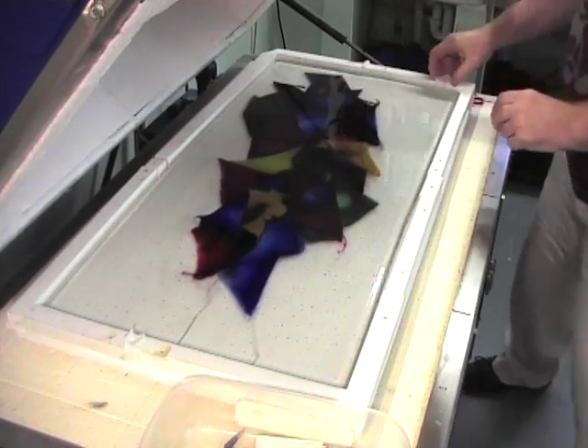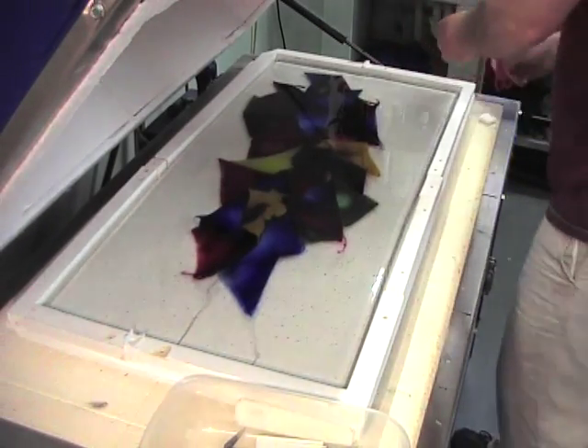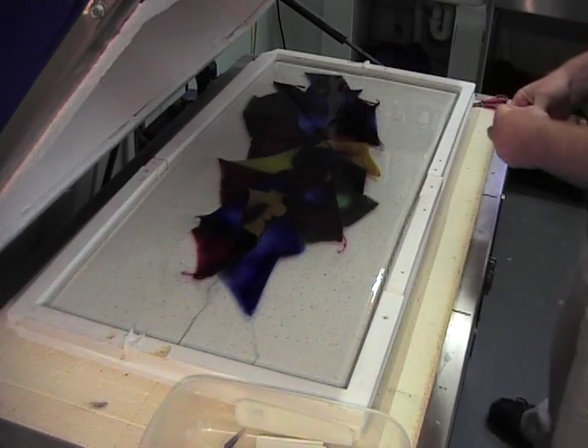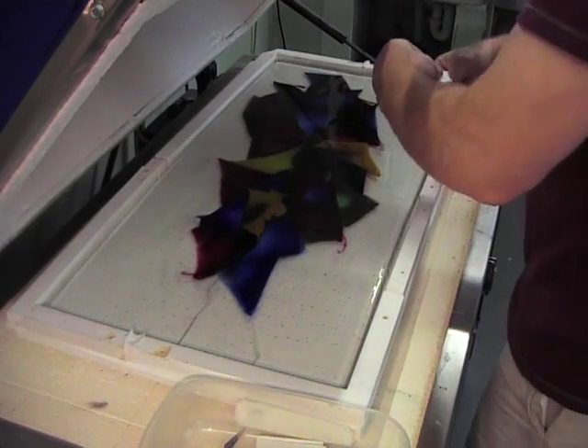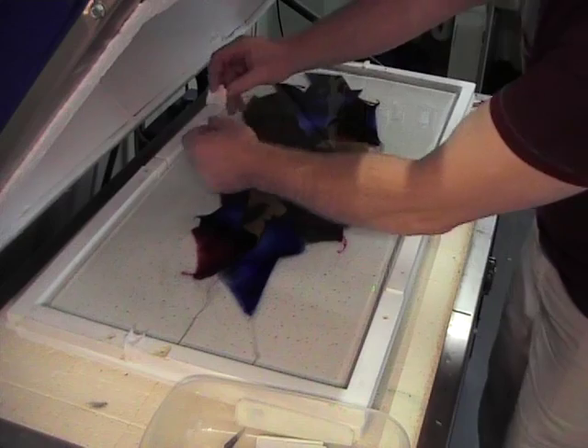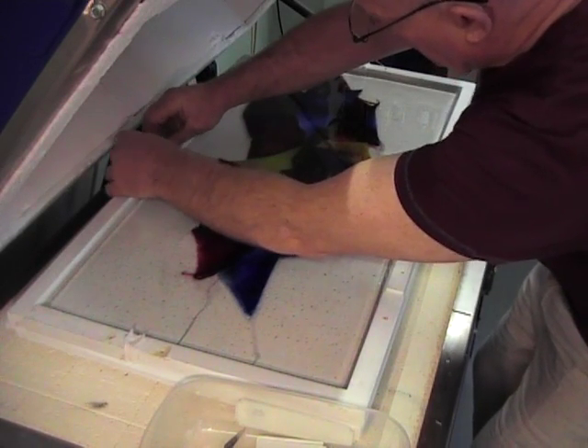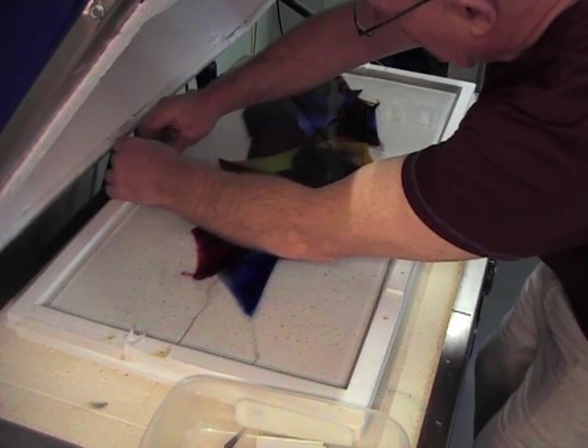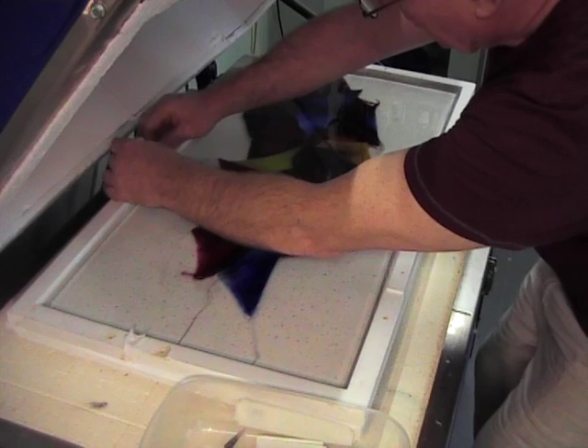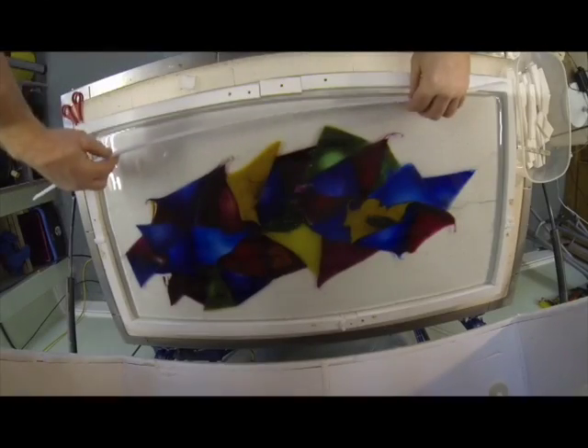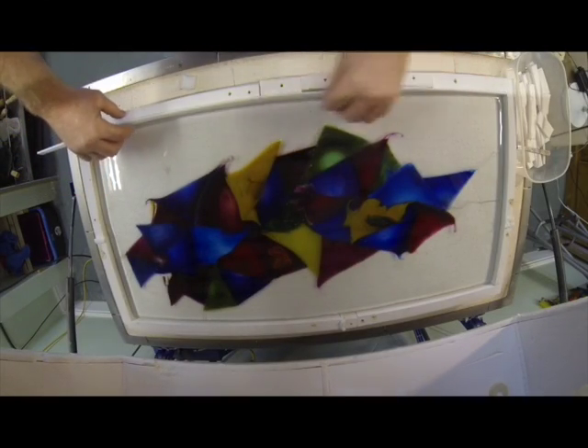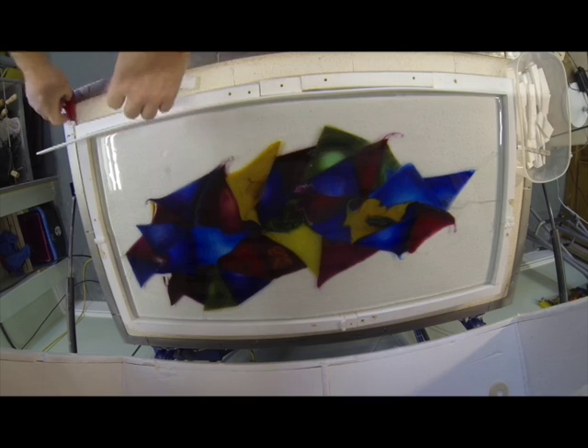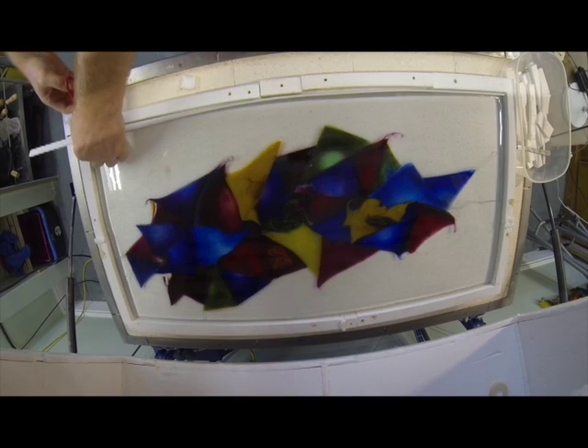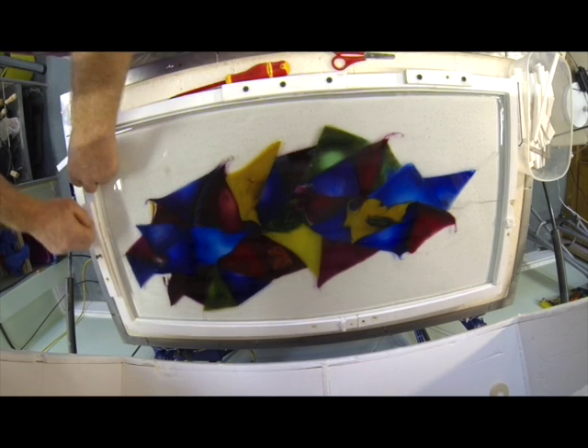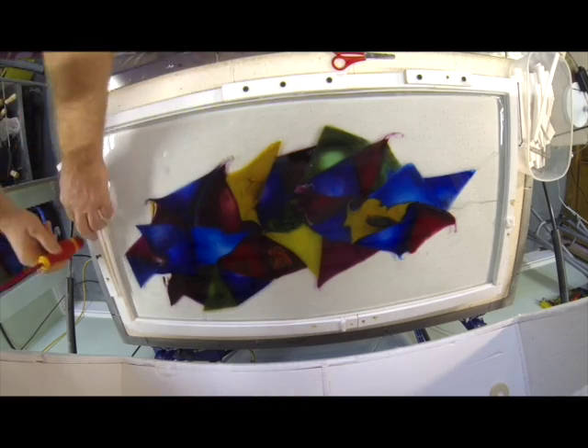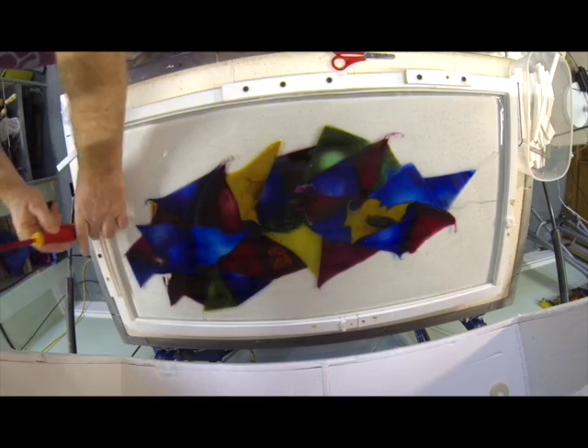The dams are made from strips of cordierite which have been cut from an old shelf. They need to be at least 20mm square and secured together. It is important to make the dam fairly robust and secure. If there are loose sections, they invariably become dislodged whilst you are raking. This becomes a big problem because you then have to attempt to reposition the section correctly back into the dam whilst the kiln is at 900 degrees centigrade. If not done quickly, the molten glass will just flow out, causing serious damage.